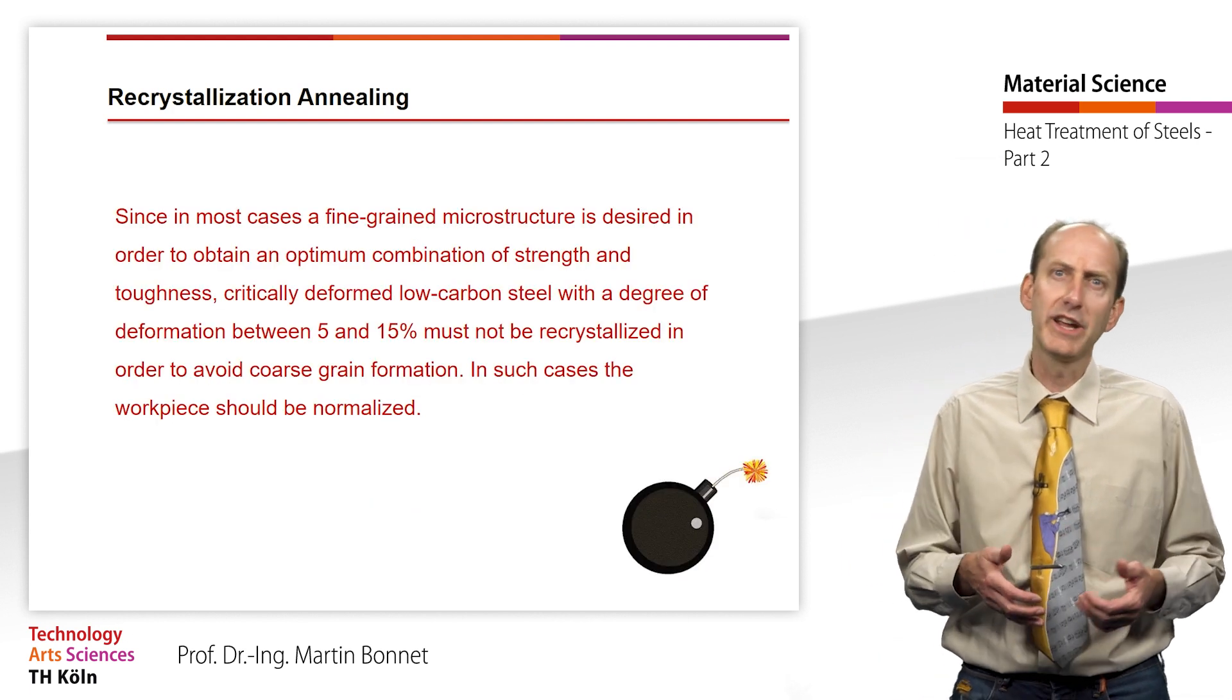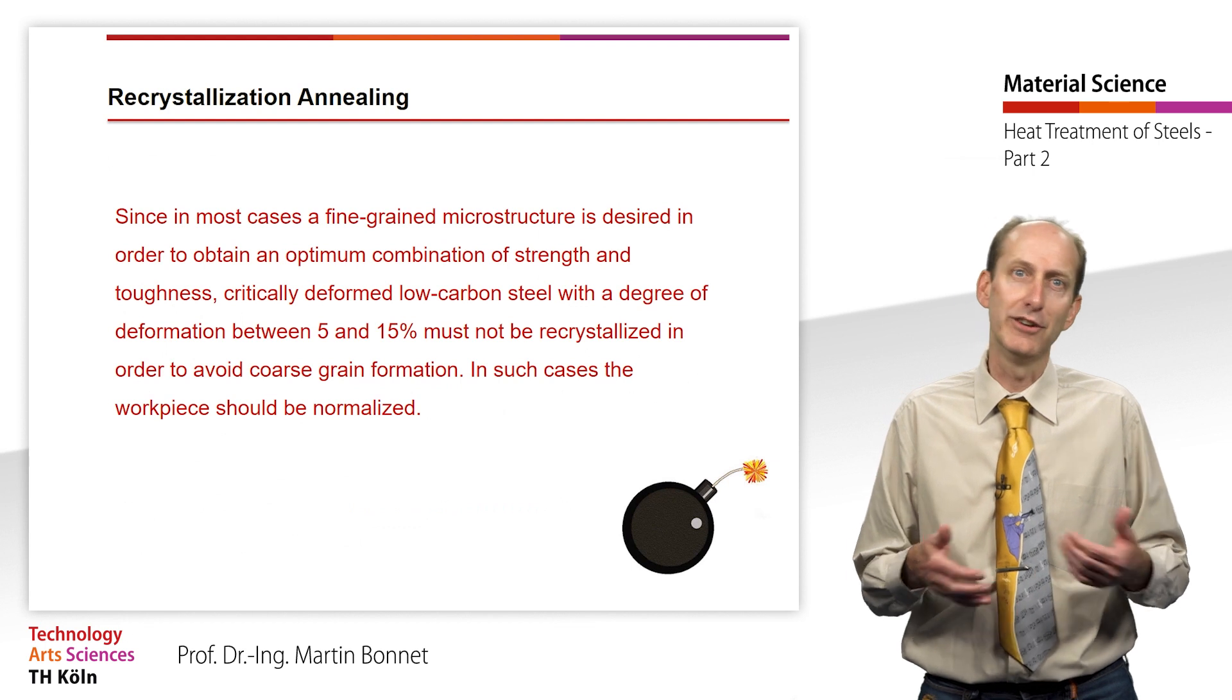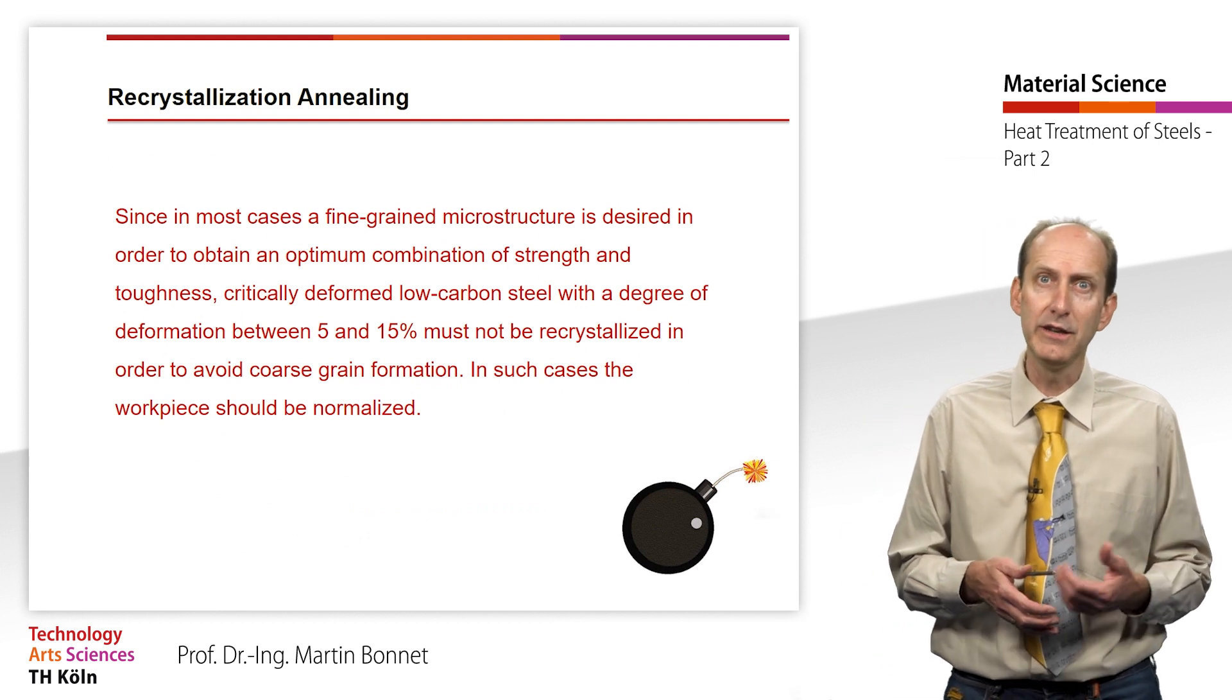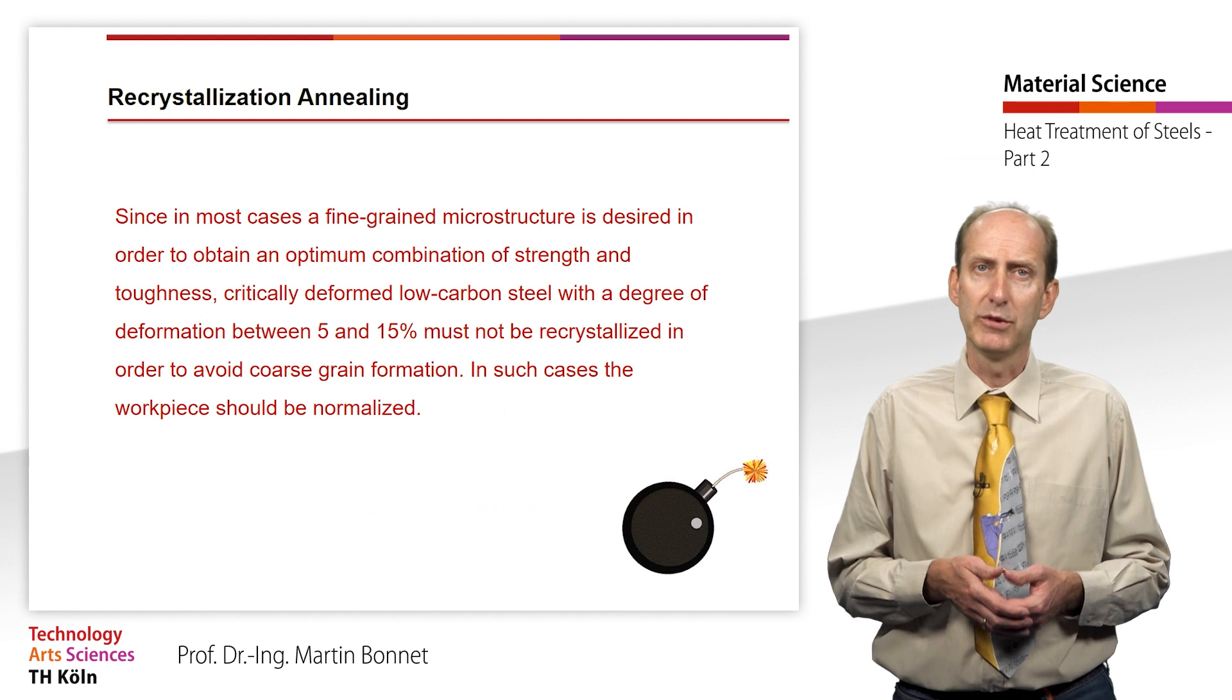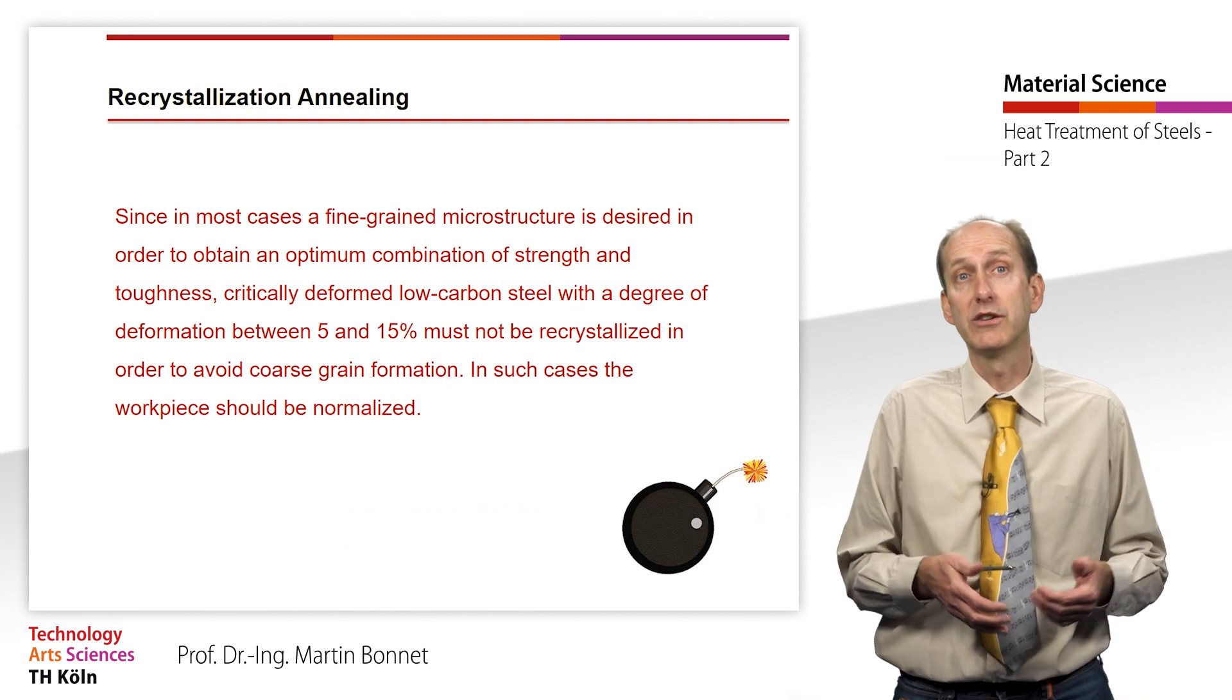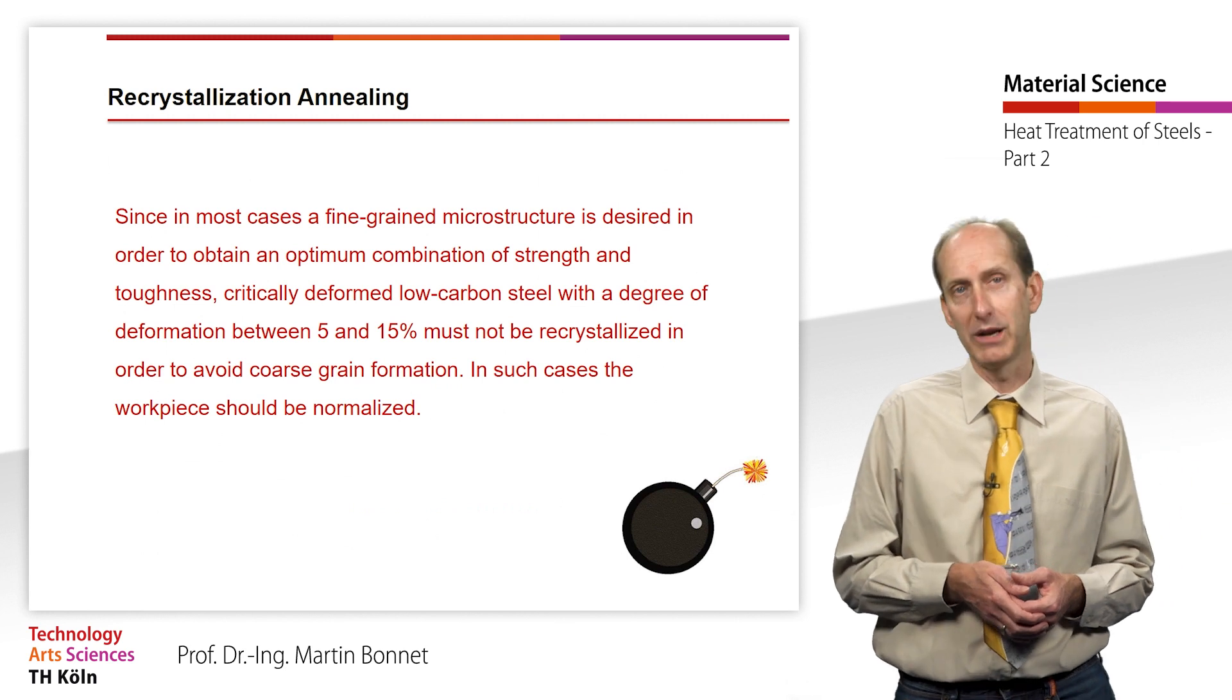Since in most cases fine-grained microstructure is desired in order to obtain an optimum combination of strength and toughness, critically deformed low carbon steel with a degree of deformation between 5 and 15% must not be recrystallized in order to avoid coarse grain formation. In such cases, the workpiece should be normalized.